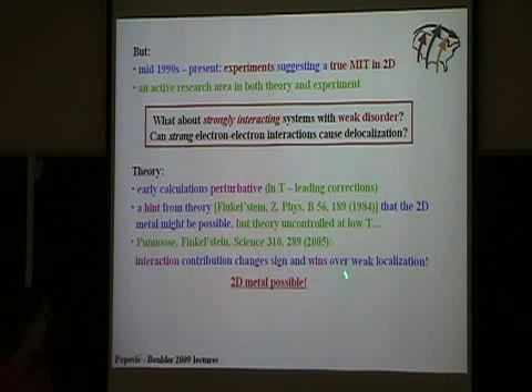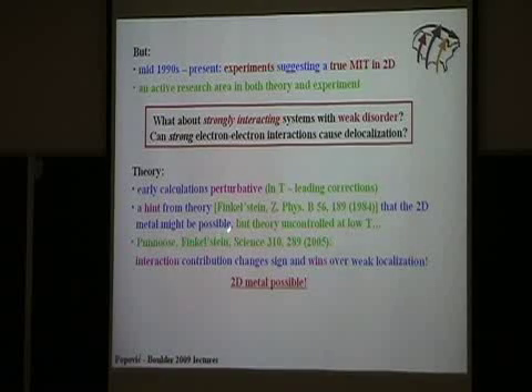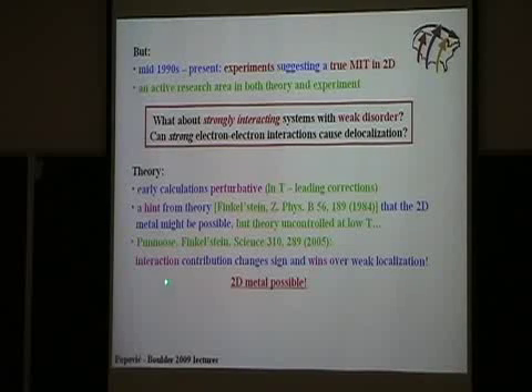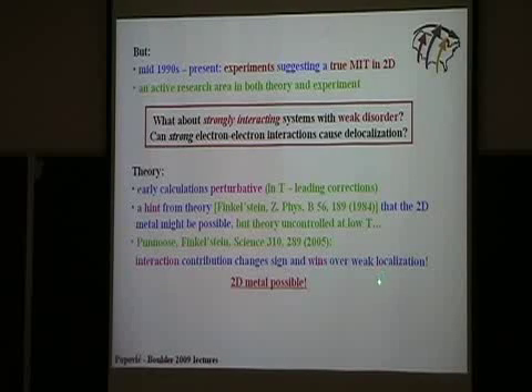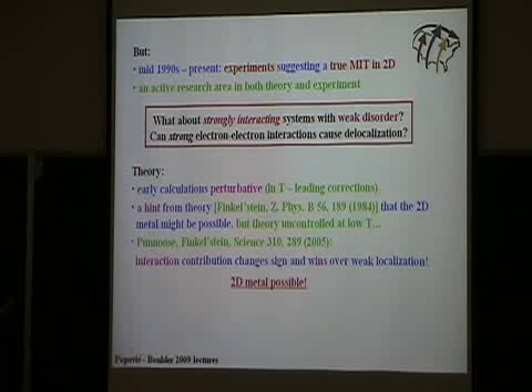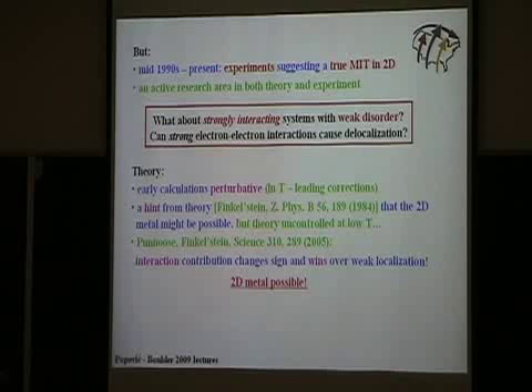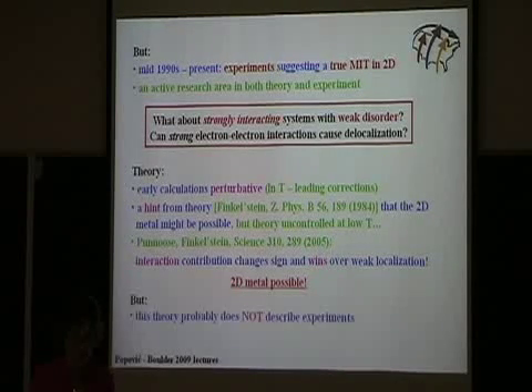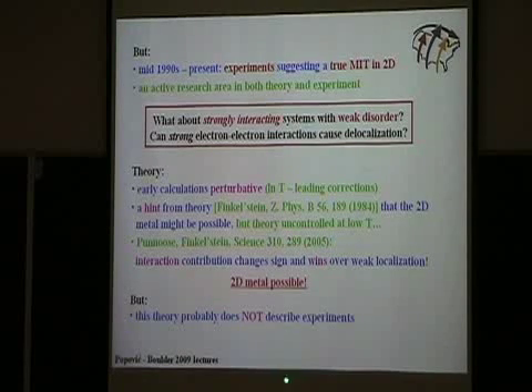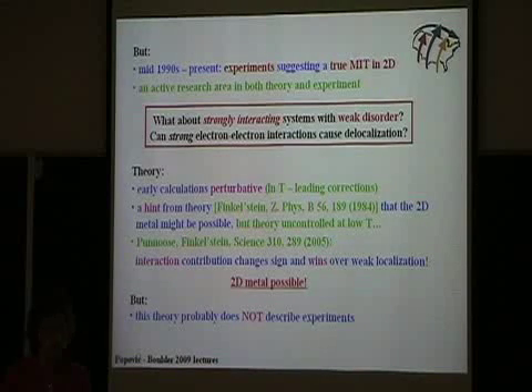And actually very recently, only a few years ago, this work was expanded, and they were able to sum all the contributions coming from the interactions and to show that the interaction contribution changes sign and wins over weak localization. In other words, as temperature goes to zero, conductivity grows, and you have a metal. So I think the theory now does show that in 2D, in principle, the 2D metallic state is possible, but, there's always a but, unfortunately, this theory probably does not describe experiments, so further work is needed to describe the real world.